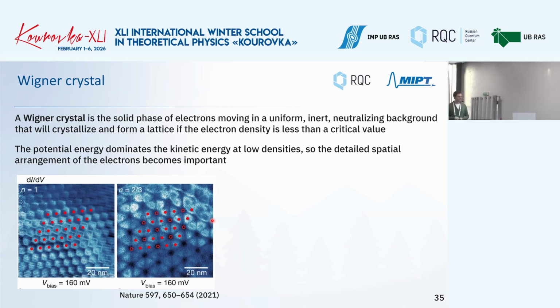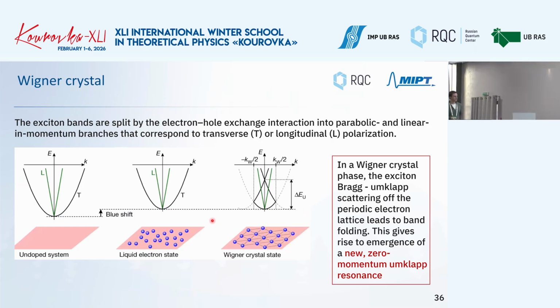And this we were able to, so you change the voltage and you change the configuration of your crystal structure. Yes, you can do it in one device just by changing the voltage on the contacts. And we were able to study this optically. Well, basically what we did, when we reach this Wigner crystal state, we find out that the reflection of the device is changing. So we can see new bands that appear in the optical reflection spectra. And when we see these new bands appearing, we can say, okay, we reached the Wigner crystal case. I will not go to the details, I'm short on time.